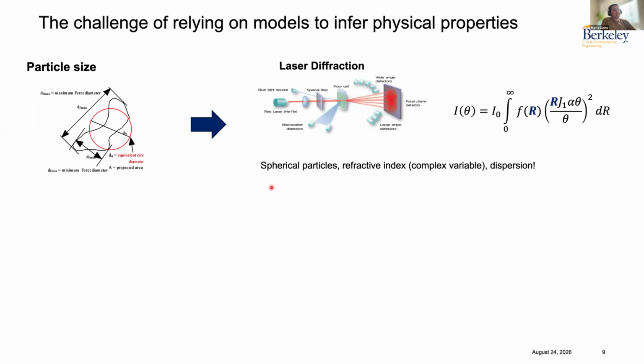However, what we actually do in cement science is that we use laser diffraction and then we use Mie theory, which involves resolving this indefinite integral function where the size, r in this case, is part of the function, which is in complex variable, by the way. And when we measure particle size distribution using laser diffraction, actually what we are doing is finding, by guessing iterations, a solution for this indefinite integral. And we take several shortcuts in order to be able to find a numerical solution for this. We assume spherical particles. We have to assume a refractive index for the media and for the particle. And again, this is in complex variables, so there is a real and an imaginary component of it. And we are also assuming that we are taking good dispersion of these particles.